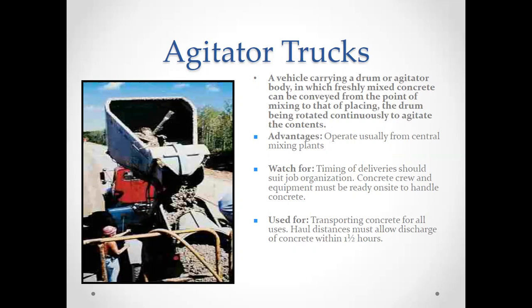So in this, the concrete is transported from one place to another, and where we are going to construct, all the material, all the tools and manual labor should be active. Whenever this concrete reaches there, the hauling and placing activity should be completed before the initial setting time of the cement without any delay. If there is a delay, then hardening of the concrete will occur. Used for transporting concrete for all uses, the haul distance must allow discharge within 1.5 hours.